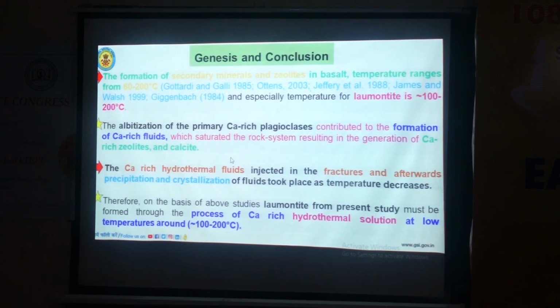So overall studies, as you know, secondary minerals, zeolites, occur in basalts and are generally found at temperatures of 60 to 200 degrees centigrade. In particular, laumontite forms at around 100 degrees centigrade. And one more is the calcium-rich plagioclase. Alteration of this plagioclase enters the calcium into solution, and that, in interaction with the saturation and with the country rocks, can form laumontite. And this hydrothermal solution, along with the planes or fracture zones or joints, can be injected, and then simultaneous recrystallization and precipitation help to form the laumontite.